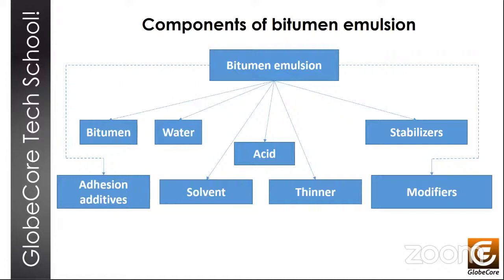The acid is needed to improve the stability of the emulsion. In most cases, we'd use hydrochloric acid or orthophosphoric acid, maybe acetic acid. In the case of anionic emulsions, however, we use alkalis, not acids.